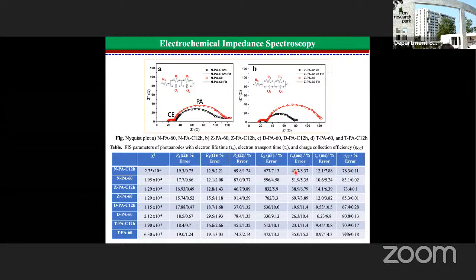Electron lifetime goes from 43 millisecond to 51 millisecond. Remember, in the previous experiment where I showed the laser photolysis, we have done the electron lifetime calculation without using iodine triiodide. We had only the electrolyte without that, inert electrolyte. Whereas here we have electrolyte containing iodine triiodide.